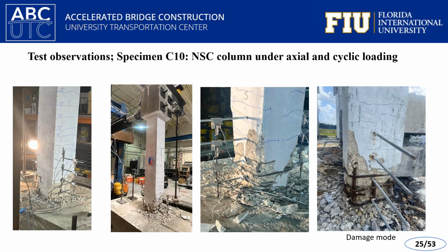This slide shows the crack propagation of specimen C10, which was a control specimen. As shown, the crack distribution along the total length of column. The stirrups remain elastic during the cyclic loading. The failure occurred when the stirrups in the plastic hinge region opened from the hooks and the longitudinal reinforcement buckled.